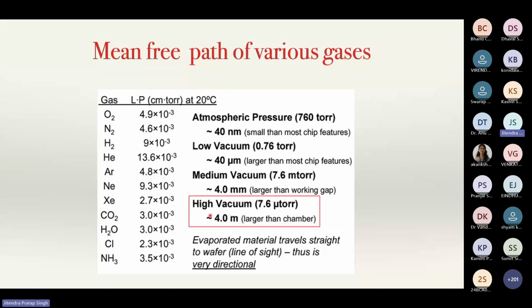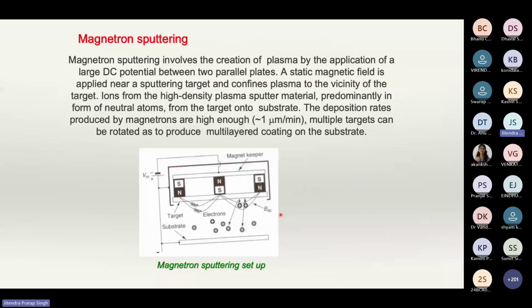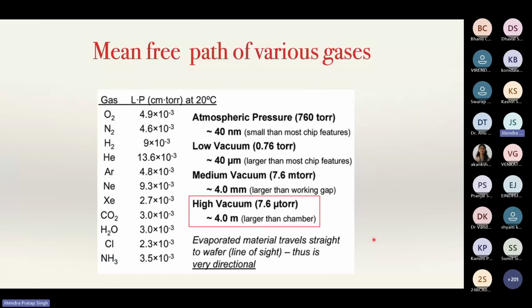What does it mean? It means that the size of the chamber is normally much smaller, less than a meter. So these atoms are not colliding with other molecules, but mainly with the chamber surface only, and we cool the chamber surface, so when they collide, mostly they get absorbed there. So you avoid interparticle molecular collisions among themselves. That will be a line of sight kind of deposition in physical vapor deposition. Whatever molecules are coming will directly deposit on the substrate. That is why you have to use high vacuum in deposition systems.